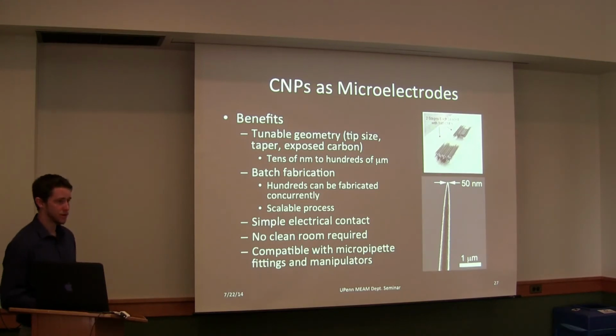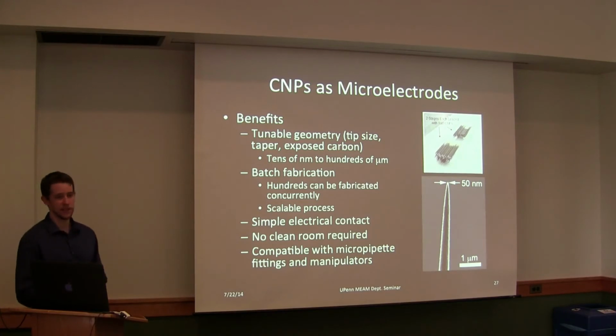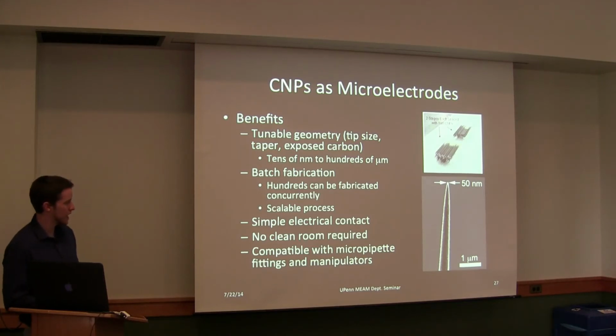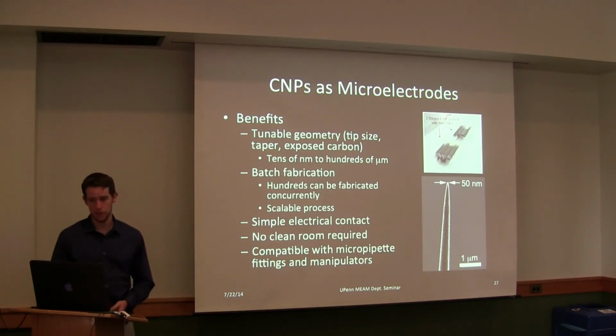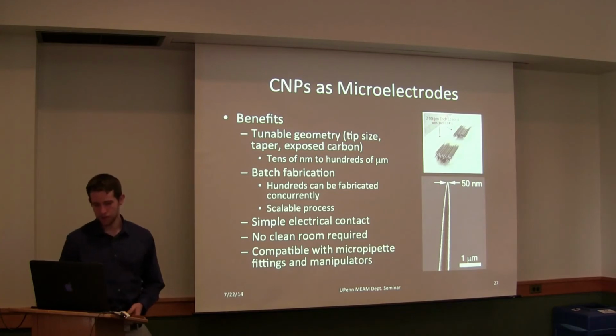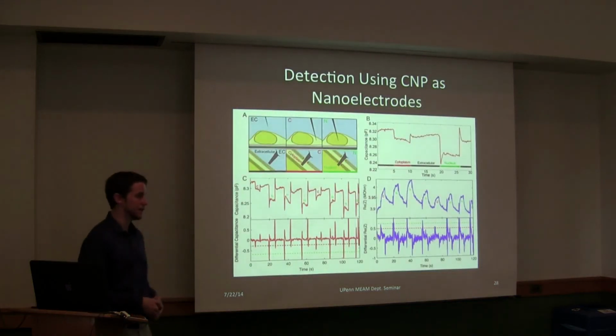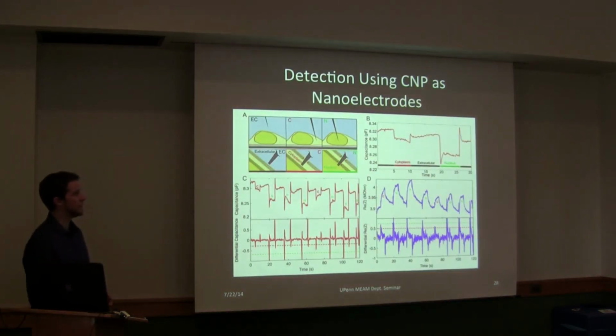And then there's also simple electrical contact. So you can basically stick a wire into the back of the CNP. It contacts the carbon lining. So that's quite easy at the macro scale. There's no clean room required for fabrication, and it's compatible with all sorts of micropipette fittings and manipulators. So one of the first things we wanted to do is see if we could detect cell penetration using CNPs as nanoelectrodes. So in fact, we can.